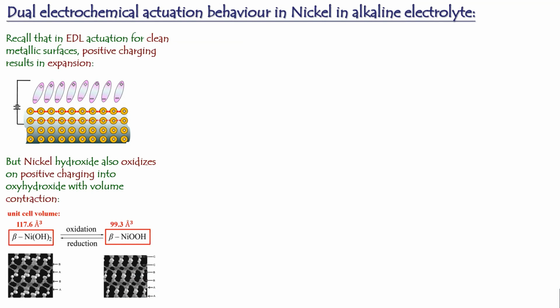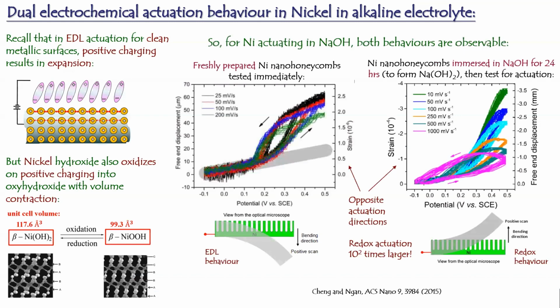So this one, I mentioned that if you positively charge the metal, it will expand because you drive the free electrons away, and therefore these nuclei would repel. So the metal would expand. For that one, if you positively charge the material, it will undergo oxidation, and then the volume should shrink. So the directions are opposite. And indeed, we observe both.